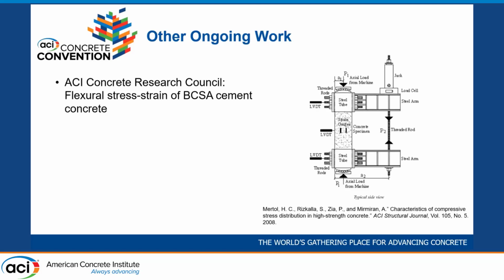So we're recreating some of these eccentric bracket test specimens. This is kind of the same type of work that was done to develop the ACI flexural strength equations. So it's kind of a crazy looking setup, but we basically have this concrete sample here in the middle. We apply an axial force and a moment to it so that we have 0 strain on one face and an ultimate strain on the other, and see what the strain distribution is.